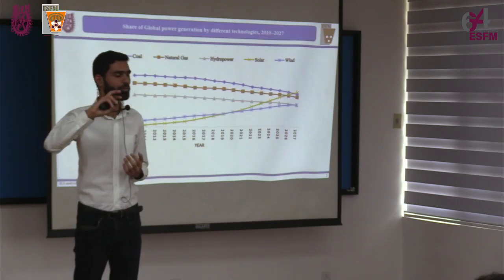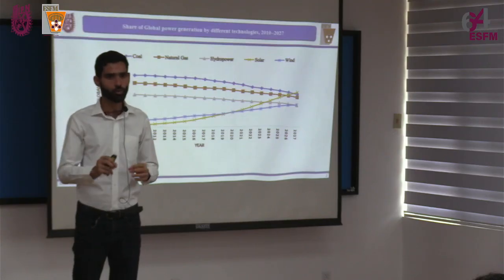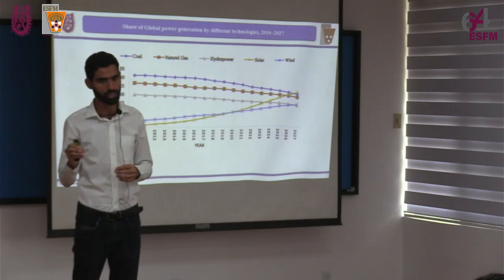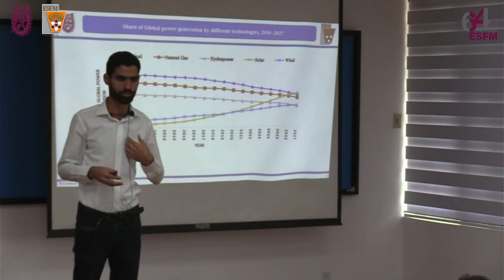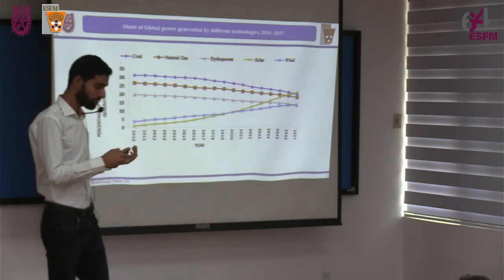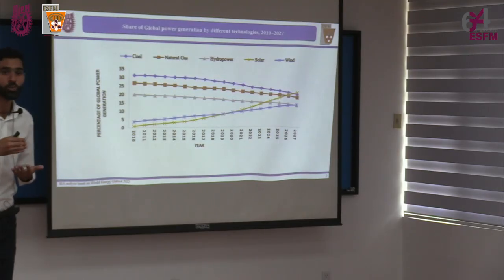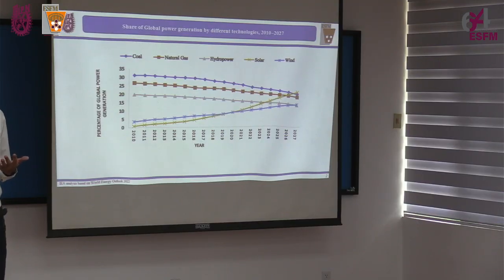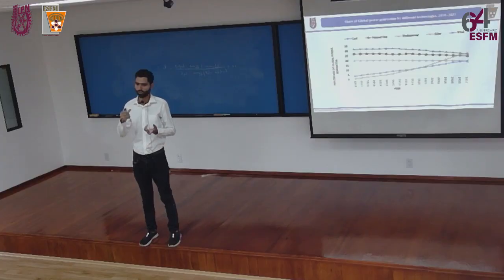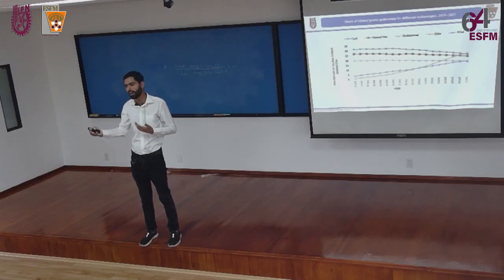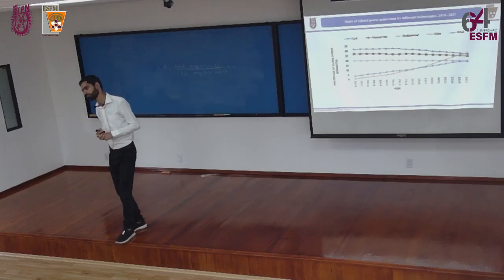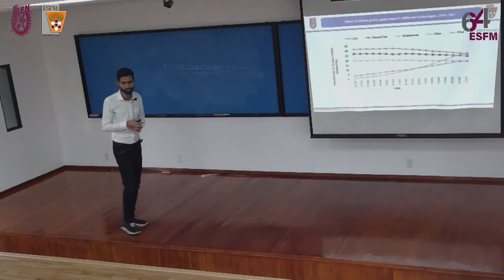And second, you mentioned 1.5, it's not the correct one. The highest reported efficiency for this material that I'm working on is 10.57. But as we saw from the characteristics of my material, we are expecting a much higher output than this, because of the optimal band gap, because of the absorption coefficient, because of carrier transfer, and also the lifespan. So with this, we are expecting much higher output from this material. That is why I'm working on it. Is this efficiency a theoretical efficiency? No, the experimental one. 10.57 is the experimental highest efficiency.